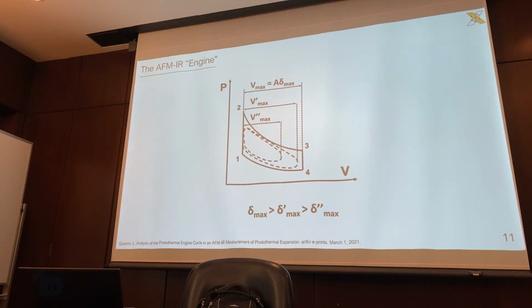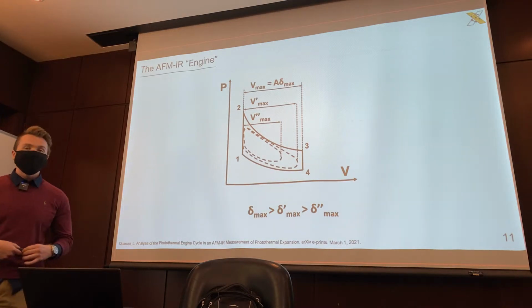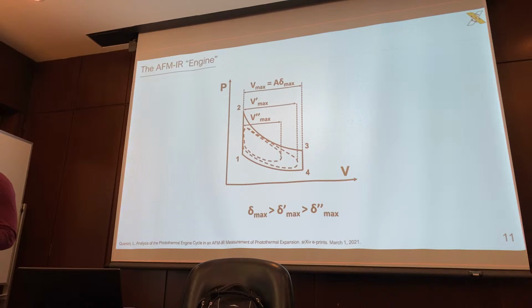So this is the actual efficiency. The ideal is the solid lines that you see from 1, 2, 3, and 4. But the deflection that we're getting out does not correspond with the actual maximum volume that we're getting from the system. And so it actually turns into a 3-part process instead of a 4-part process, because we're losing the actual movement from 3 and 4, and it's becoming a single point here.